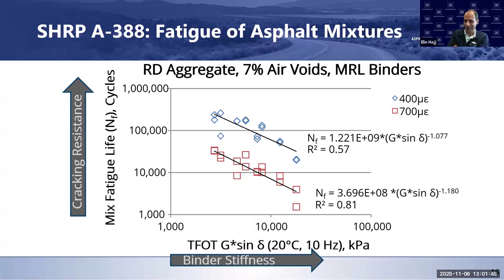But one of the questions is again related to using high recycled material, whether it's RAP or RAS, by allowing some binder replacement up in the 30 to 40% range. I think the concern is that there are long-term durability issues that may not show up on the PAV, DSR, BBR, or even the mixture testing, like the IDEAL-CT or maybe the Hamburg wheel tracking test. So the question is basically whether there is any research plan to find mitigation strategies for these concerns. There's binder testing from one side that you may not be able to capture that, but also if you switch to the mix and you try to focus everything on the balanced mix design, there are also some limitations on some of those tests.